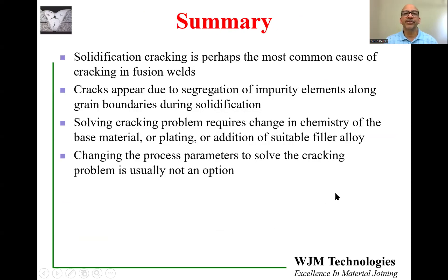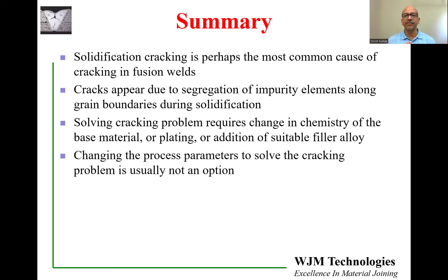In summary, solidification cracking is perhaps the most common cause of cracking in fusion welds. Cracks appear due to segregation of impurity elements along grain boundaries during solidification — this segregation happens in every weld, but whether it causes cracking depends on whether the segregated material has a very low melting point or weak cohesion properties. Solving cracking problems requires a change in chemistry: either change the base material, the plating composition, or add a suitable filler alloy. It is not possible to solve solidification cracking by changing process parameters such as power, time, or cooling.